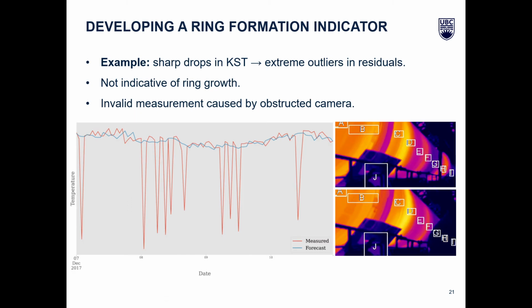Here, I present an example that demonstrates the problem with using the extreme outliers from the temperature residual as ring indicators. This example shows the cause of the uncharacteristically sharp temperature drops observed in the shell temperature measurements. The figure on the left provides a closer view of these temperature drops that become upward spikes in the residual. The figure on the right shows the raw thermal camera images taken from the same period. Note that measurement area G corresponds to the 60-foot position.